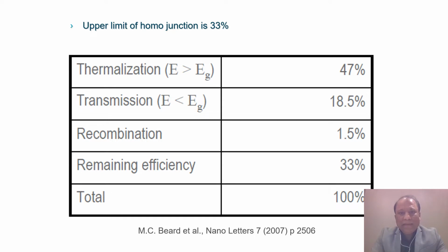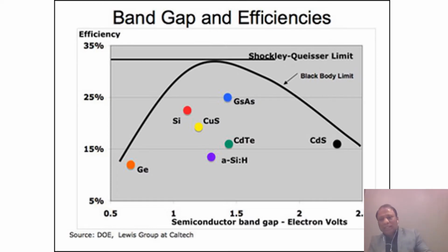As far as homojunction is concerned, the maximum limit is around 33%. If you have photons with energy more than the band gap, they will be absorbed, but the rest of the energy will be wasted. That is thermalization. If the photons have less energy than the band gap, then 18.5% is gone, and recombination takes 1.5%. Then the remaining efficiency is only 33%. This is the well-known Shockley-Queisser limit, and it depends on the band gap, isn't it? The optimal band gap is around 1.4 to 1.5 electron volts.